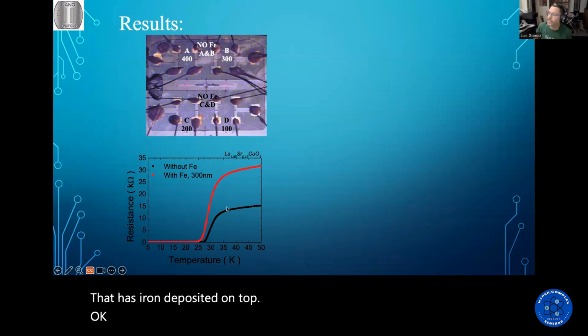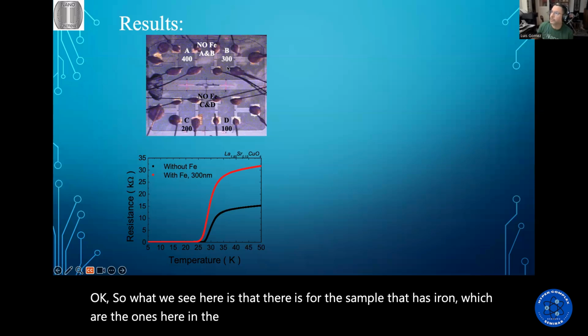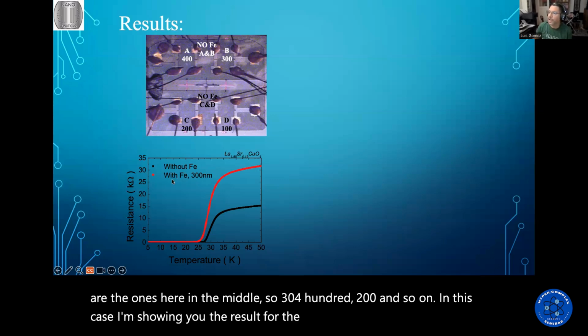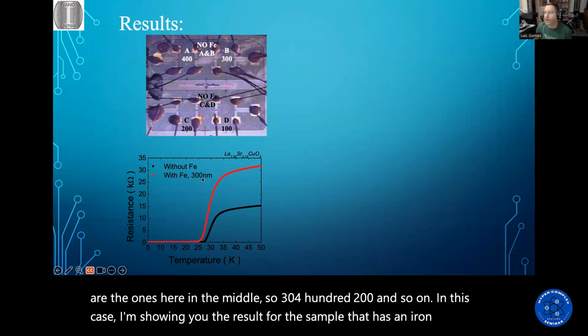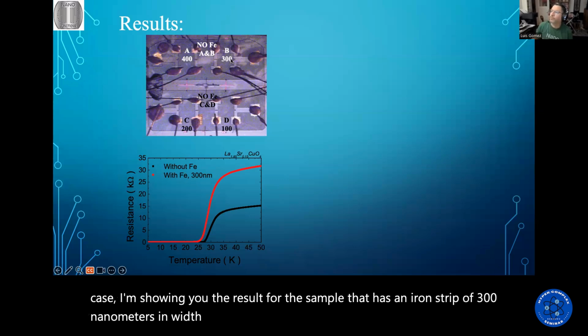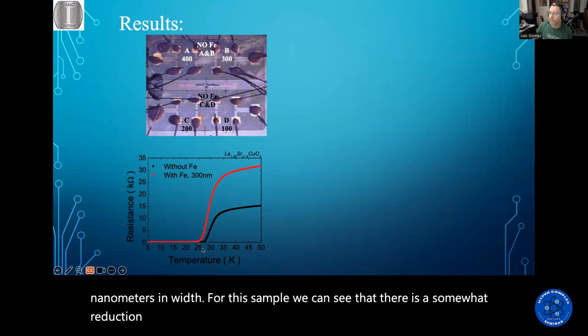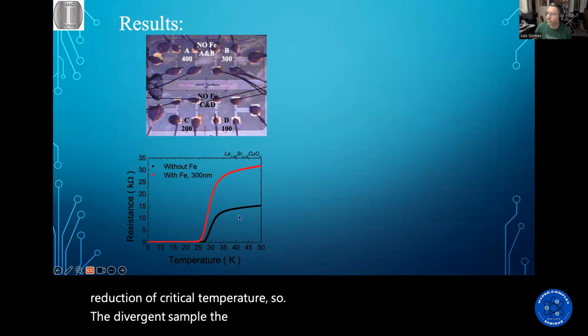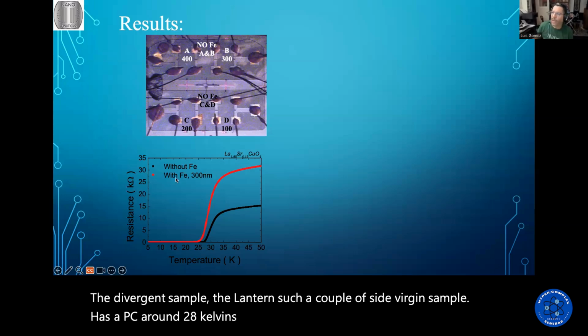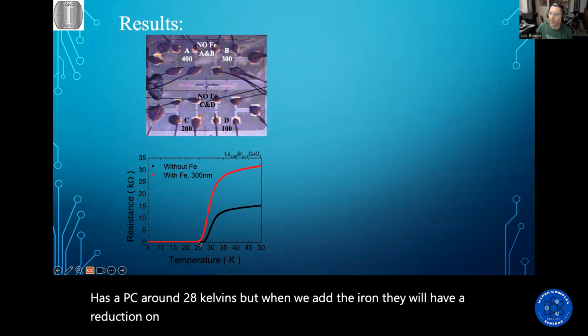Okay, so what we see here is that for the samples that have iron, which are the ones here in the middle, so 300, 400, 200, and so on. In this case, I'm showing you the result for the sample that has an iron strip of 300 nanometers in width. For this sample, we can see that there is a somewhat reduction of critical temperature. So the virgin sample, the lanthanum strontium copper oxide virgin sample, has a TC of around 28 kelvins, but when we add the iron, then we'll have a reduction in this critical temperature.